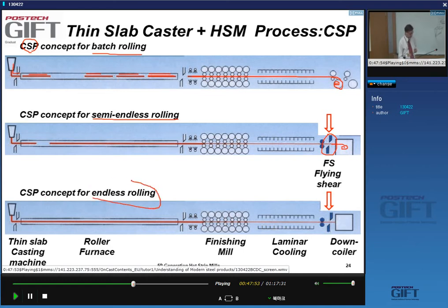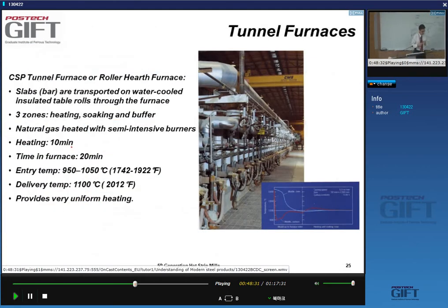And in principle, you could do endless rolling, yes? Casting, go right into the finishing mill, the cooling, and then down to the coiler, and in order to make individual coils, you'd again need to have a flying shear. Obviously, this technology, this endless rolling, is only possible if you have a very thin strip, yes? And your casting speed is high enough, as I explained.